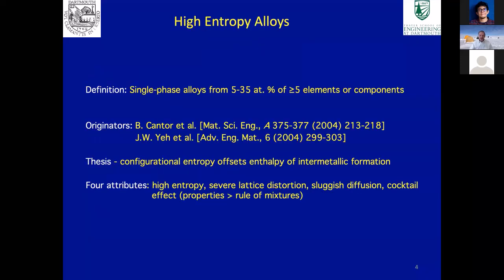So let me start out with the definition of high-entropy alloys. They are single-phase alloys, which have from 5 to 35 atomic percent of at least 5 different elements or components, and by components, we mean they could be oxides instead. The originators of high-entropy alloys were Brian Cantor and J.W. Yeh, and it was actually J.W. Yeh who came up with the name high-entropy alloys. And the idea was that for a high-entropy alloy, the configurational entropy offsets the enthalpy of intermetallic formation so that you end up with a single-phase material.